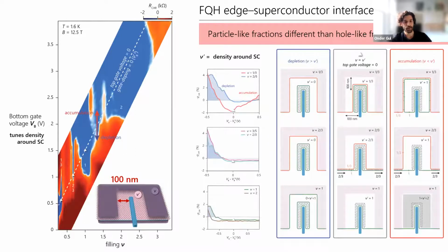This difference could be related to details of the edge profiles for particle-like and hole-like fractional states. We have made a schematic in which we depict the relevant edge profiles based on the understanding gained from fractional quantum Hall experiments in the past decade, maybe a bit longer. We also include the potentially present residual edge modes around the superconductor formed by contact-induced doping related to a Fermi level mismatch. This is expected in the device because the Fermi levels are very different in niobium nitride and graphene, and there can be such doping. This is, of course, unintentional, but it may be very difficult to avoid in this kind of geometry. These residual edge modes are shown as dashed gray lines.